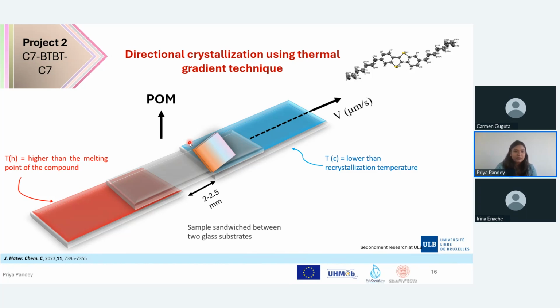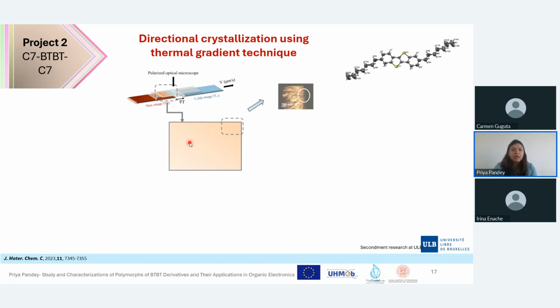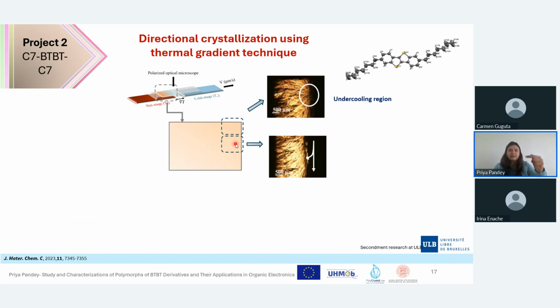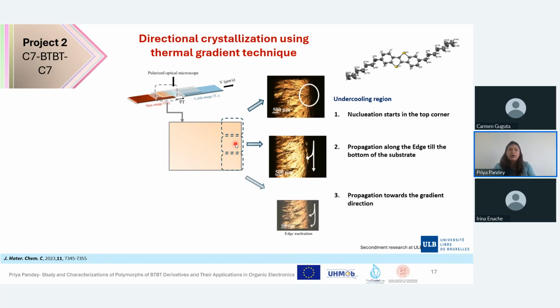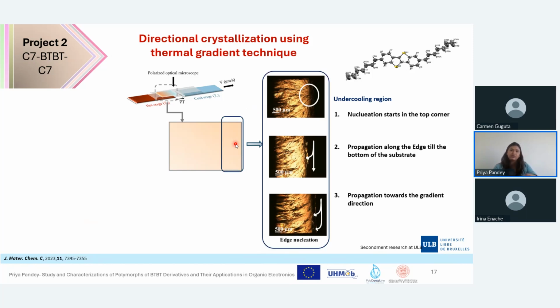This is quite an impressive technique because we can tailor a lot of different conditions for the crystallization. What happens when we use this kind of technique for our molecule is that we can see a nucleation point, and there can be multiple nucleation points depending on the pulling velocity. Then we can see the crystals trying to reach the fastest reachable cold end, which is usually in the vertical direction, not always. Then we can see the propagation of the crystals towards the gradient direction. And this whole region, the first region on the glass slide, is called the undercooling region. This is where the nucleation takes place, basically.